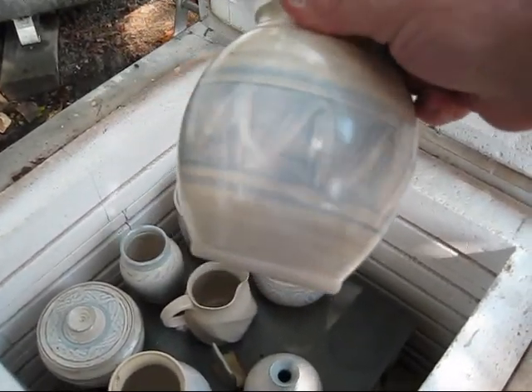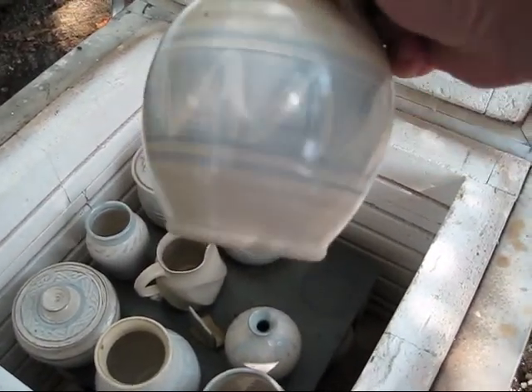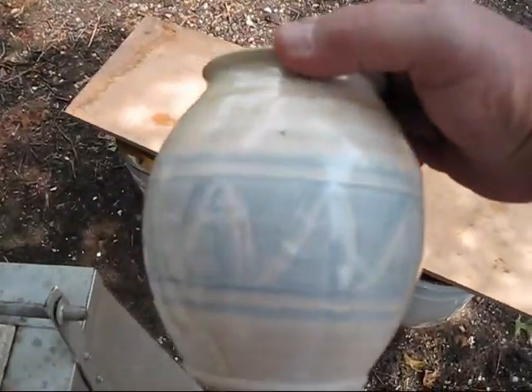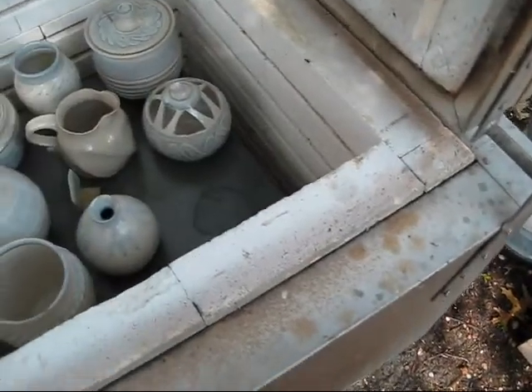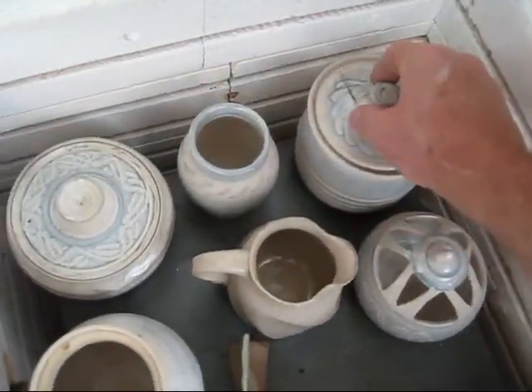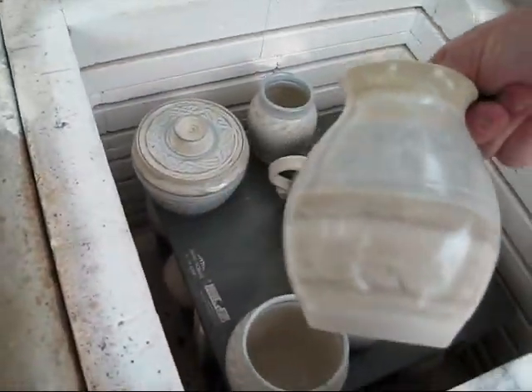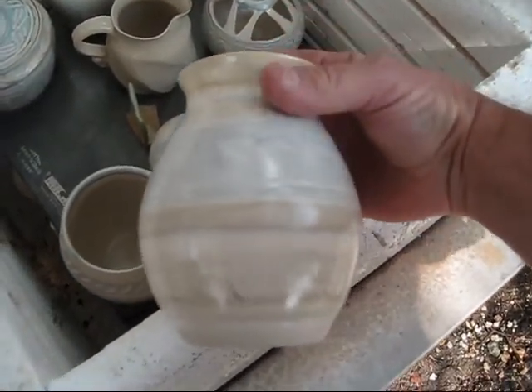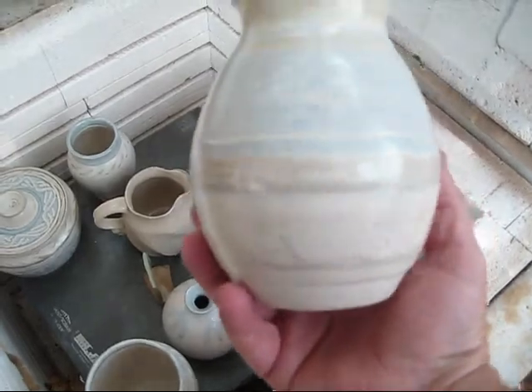Nice pieces for the slip. All these have the same Simon Leach's white glaze over top. Some are porcelain, some are my white clay, with a little bit of slip. This yellow I've been trying to get to come through just didn't work — I used a yellow iron oxide. I tried another slip around the edge in blue, you can just barely make it out, so I have to darken that up. This little vase is brown — I have a dark chocolate clay that I made this out of. Before it gets cooked it looks great, but it kind of loses all its color.